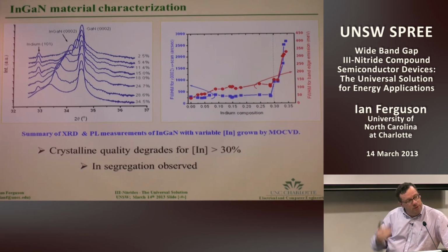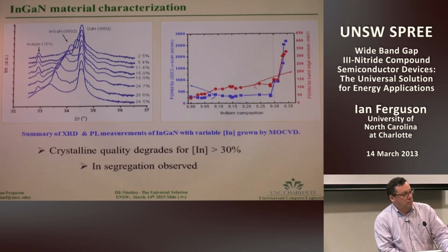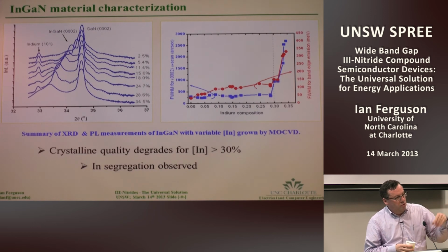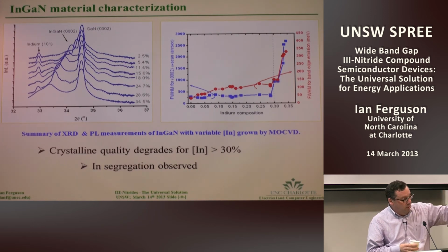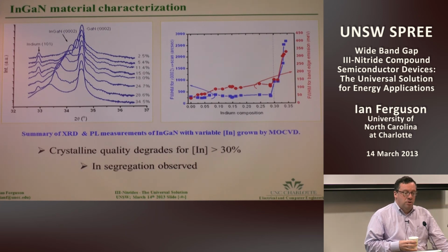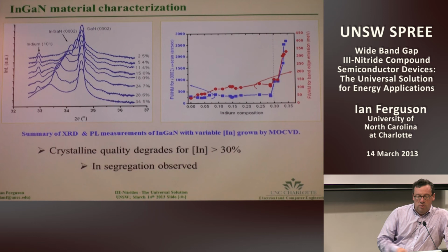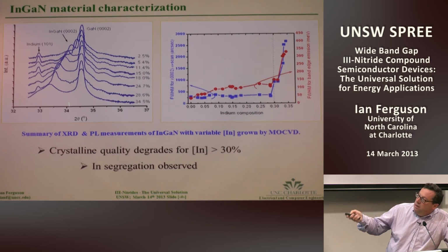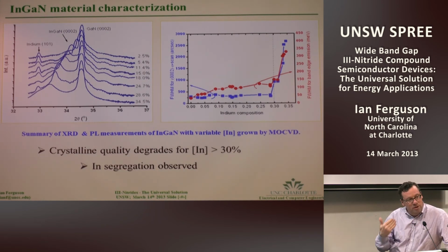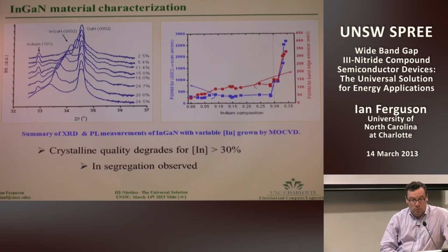Other issues we had is that, in our work, most people had grown these materials for solid-state lighting applications. What you were typically doing is growing these essentially five monolayer thick quantum well regions, where you were causing the material to phase separate to get compositional fluctuations, localize the emission, and give you very bright emission. The issue with solar was how do we suppress that, and up to what composition could we suppress that? So part of what we were trying to address, and this is X-ray and PL, is how do we suppress this to get homogeneous gallium indium nitride?